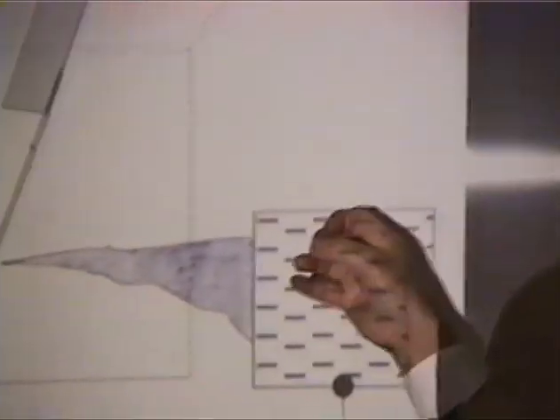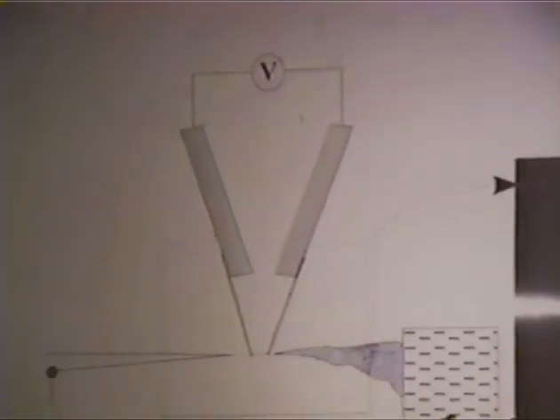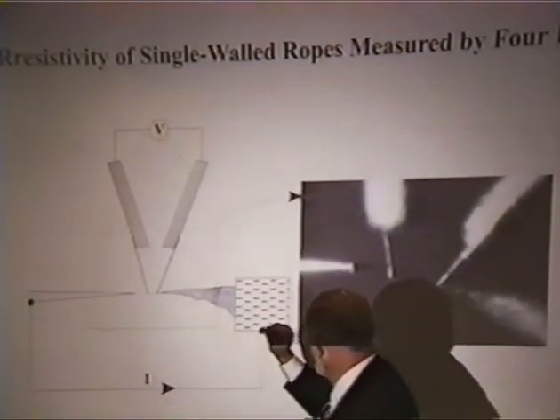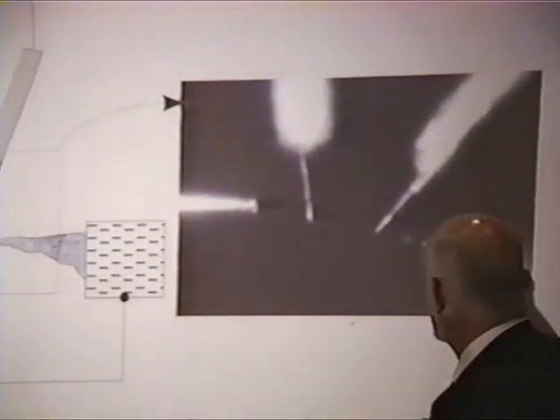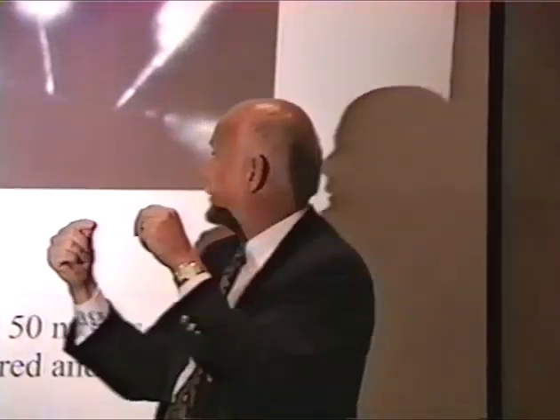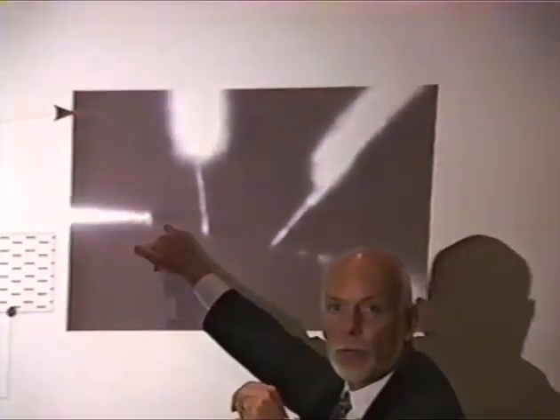And here's a piece of this felt that's actually held in a little alligator clip. And over here we have a platinum needle that's been electrochemically sharpened. We first stick that needle a couple microns into the stickum on Scotch tape and then pull it back out. Put a little stickum on the end of the needle, and then we shove it into the felt and pull it back out, and usually one of these ropes in the felt will get tangled in that glue, and as we pull it out, it ultimately starts pulling the felt tangle behind it. And you can't actually quite see this rope here, but you know it's there because as you pull the needle, it follows it up and